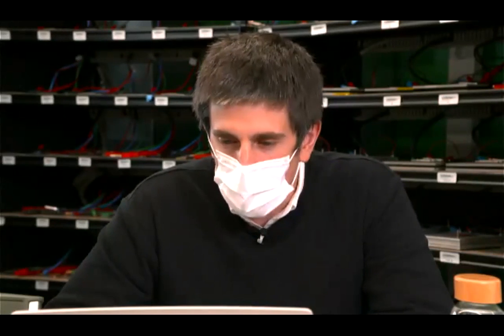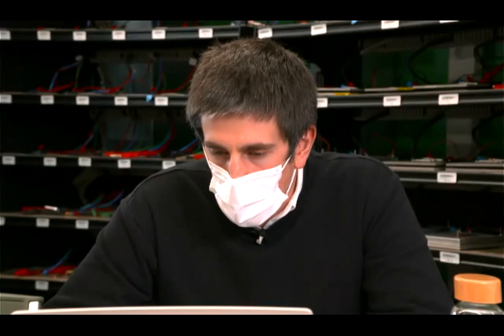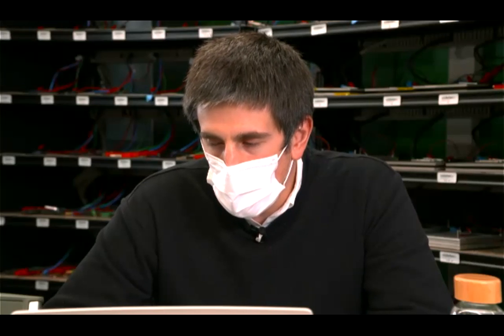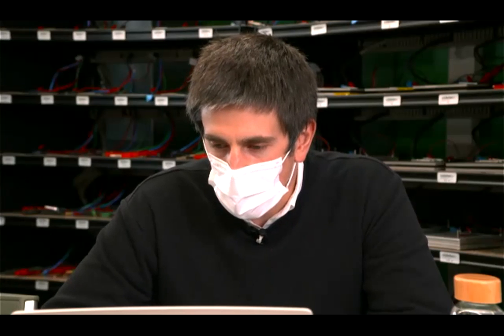And also, depending on the chemistry, we are doing some formings with temperature, or we are doing different than one cycle at C/20. So that is specific to each cell. But for example, working at 40 degrees in a forming for the formation in the cell, you are ensuring, with the time that the electrodes are soaked and also with this forming at temperature, that you make it easy for the electrolyte to penetrate, because with this temperature, the density of the electrolyte can vary and can facilitate this electrolyte soaking of the electrode.